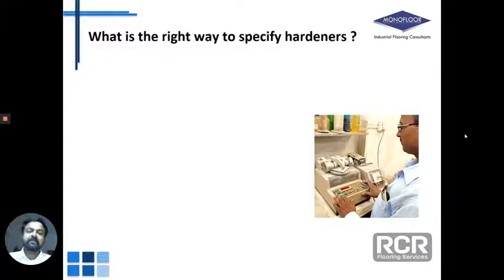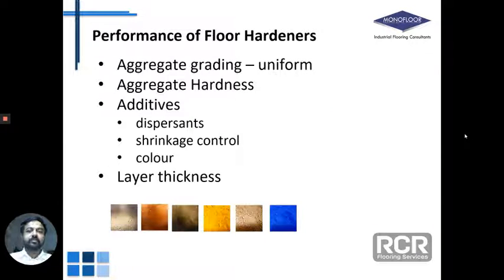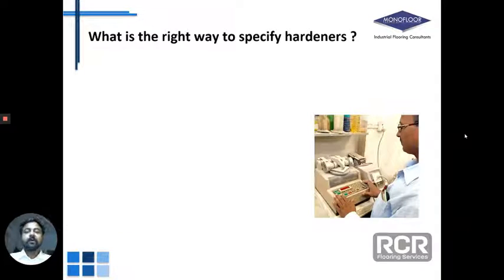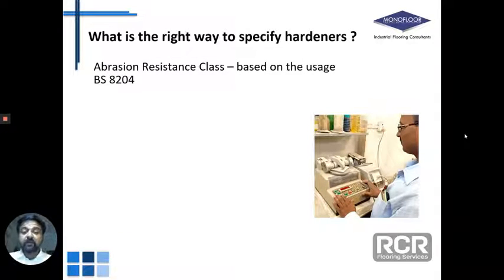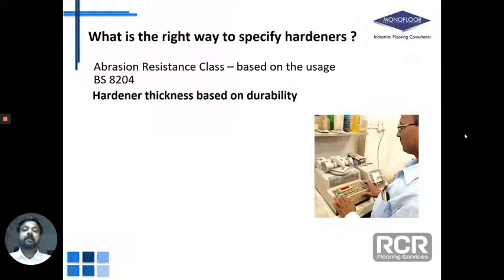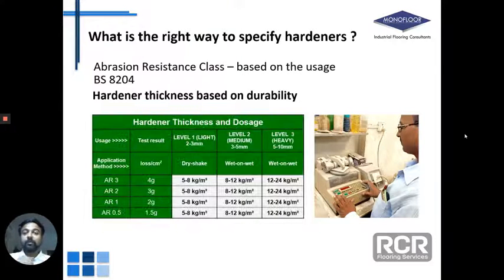And of course the layer thickness is an important parameter when it comes to finally assessing the durability of a hardener layer. So layer thickness is very important to give you durability for the hardener surface. When it comes to how we specify hardener, the right way to specify hardener thickness is based on durability. Like I said, kilograms per square meter is the only thing that can give you thickness. Now talking about the abrasion class, depending on what vehicles or what kind of equipment you are moving on the floor, you need to decide the abrasion class.